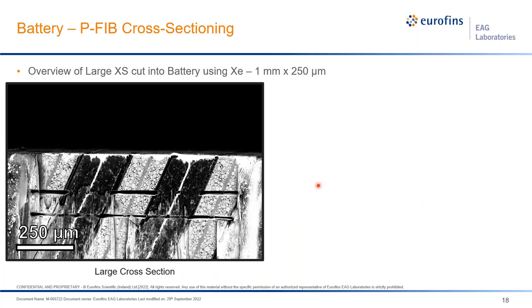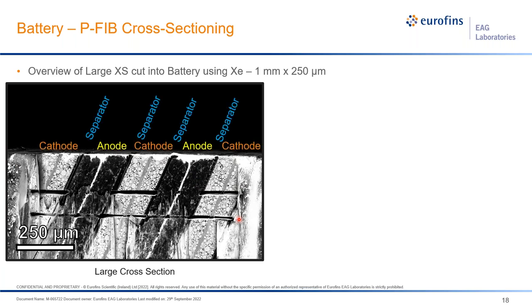So here we can see an overview of a very large P-FIB cut. In this case, we're looking edge on at 90 degrees to the sample, and we've made a 1 millimeter wide by approximately 250 micron deep mill into the side of the battery. Here, this exposes a couple of the repeat units of the structure: cathode, separator, anode.